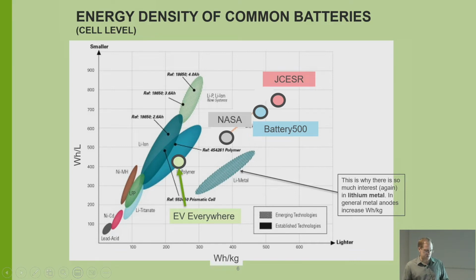So in Thomas Edison's day, he was working on these aqueous batteries down in here. So here's lead acid. This is a modern day lead acid battery. So it's about 25 watt-hours per kilogram. Then you had your nickel cadmiums, and they were being replaced by nickel metal hydride. So that nickel iron battery is in this ballpark. So with lithium-ion, when that came out, that's this oval here. Lithium ions were down here, then they kind of moved up into this region. Then you have lithium polymer. So lithium polymer, a little bit higher energy per gram, but a little less on watt-hours per liter.